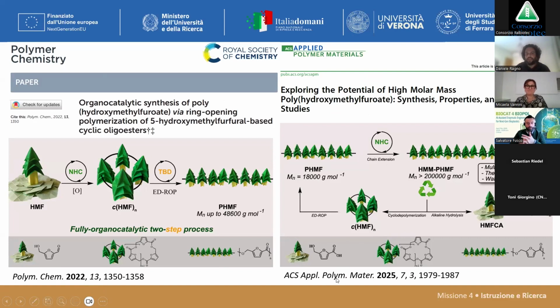In a more recent publication, we were able to introduce a chain extension stage, increasing the length of the polymer. We were able to film it and study water contact angle, and in all these works we always study the structural, thermal, and behavioral aspects of our polymer.